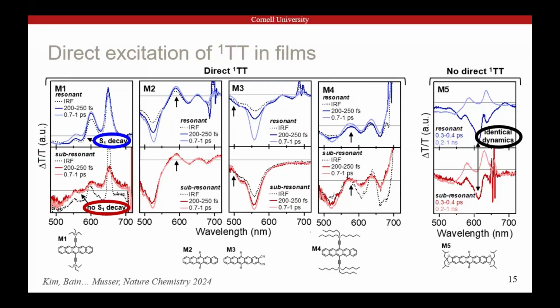Fortunately for us, singlet fission gives us a way to at least infer the answer, because forming this triplet pair state isn't the end of the fission process, it's only the beginning. Once the triplet pair is formed, they can hop apart, they can undergo various spin evolutions, they recombine, they can evolve into these high spin quintet pair states and the like. And all of these things are deeply tied to the ability of the triplet to move, which is tied to nearest neighbor couplings. So if the local environment of your triplet pair state is unique, you're going to have distinct triplet pair or triplet transport dynamics. So you're going to see that in the subsequent evolution of the pair state.